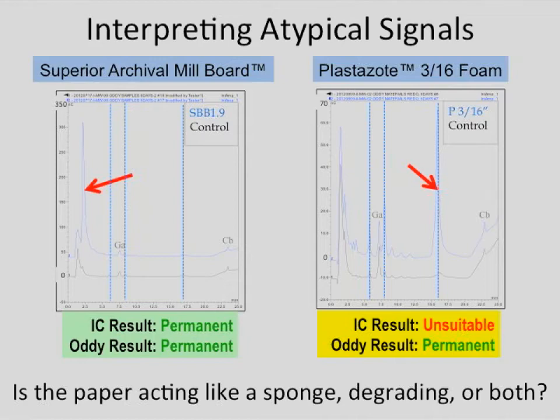In this case, if we just analyzed using the method I showed you before, we would say this is permanent, go ahead and use it. It doesn't seem to be degrading the paper. In other words, if these are the only paper degradation products we're seeing, it doesn't seem to be doing anything to those. So what's happening? Is this just something that's absorbing into the paper and sitting there, and then maybe slowly evaporating, or maybe sitting there not doing anything, acting like a sponge but not affecting the cellulose structure?